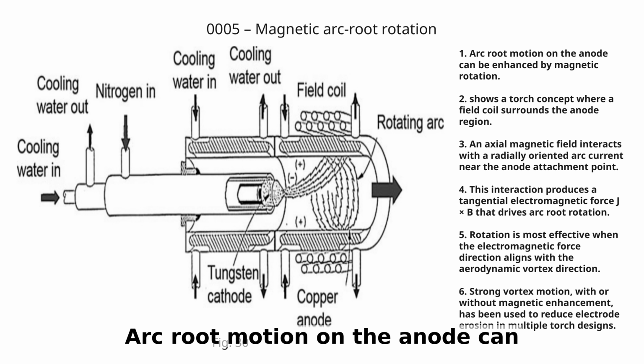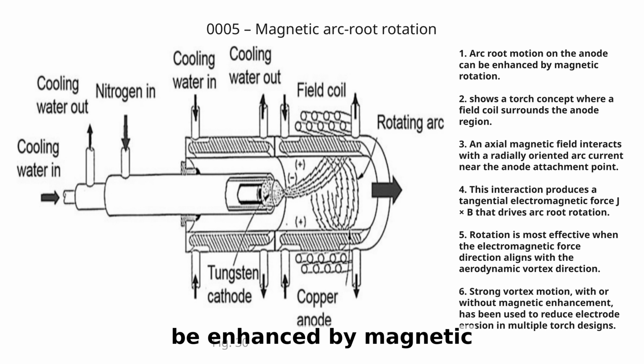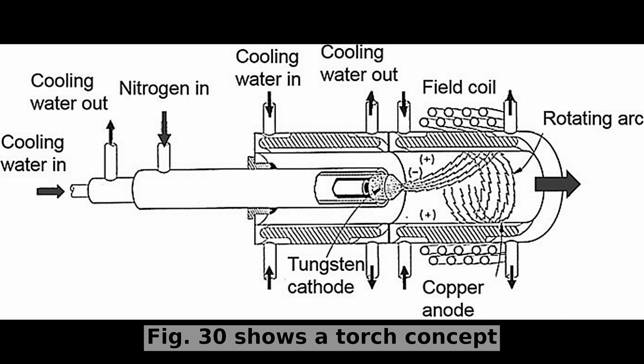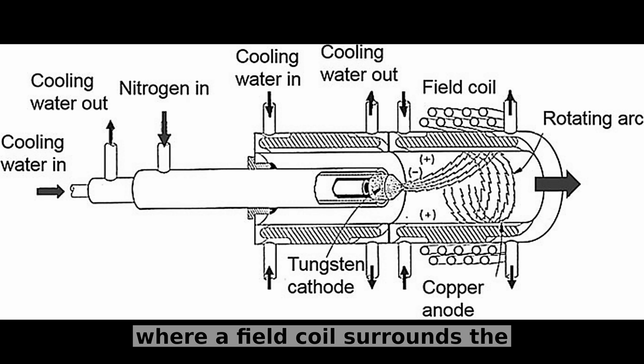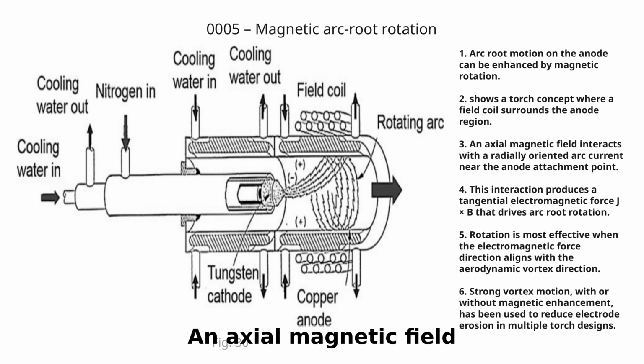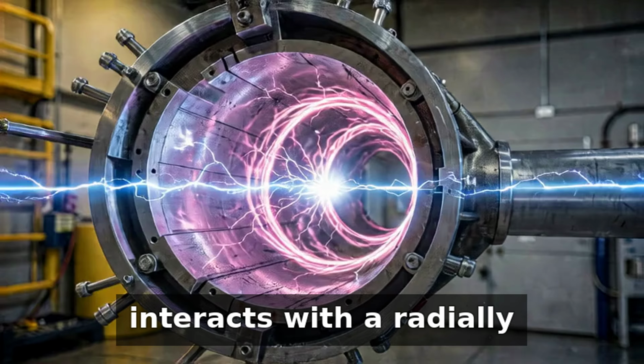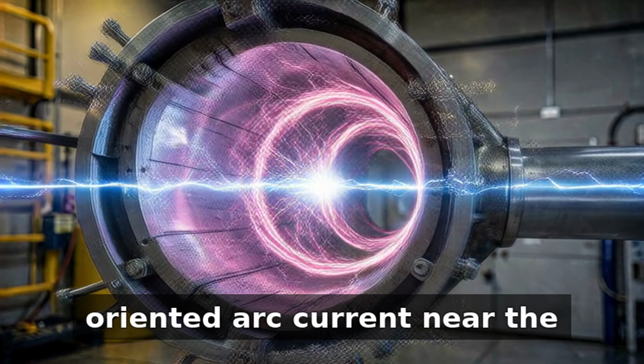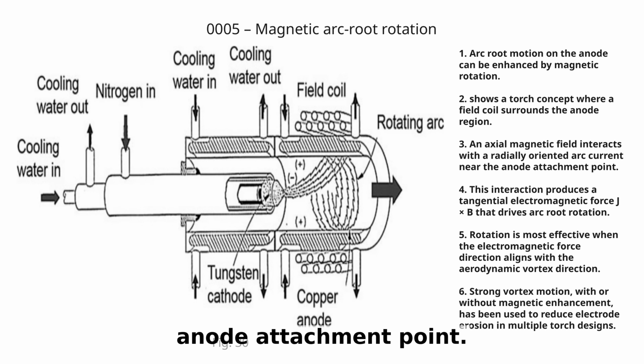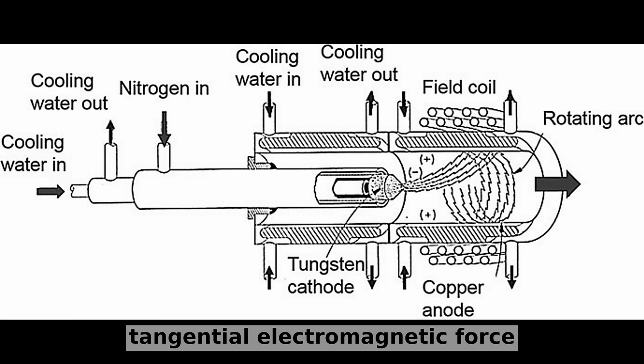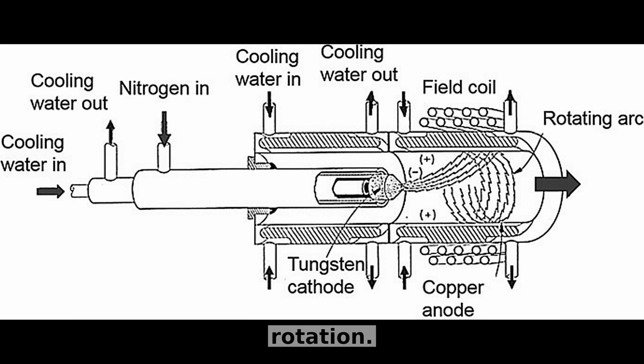Arc root motion on the anode can be enhanced by magnetic rotation. Figure 30 shows a torch concept where a field coil surrounds the anode region. An axial magnetic field interacts with a radially oriented arc current near the anode attachment point. This interaction produces a tangential electromagnetic force J cross B that drives arc root rotation.